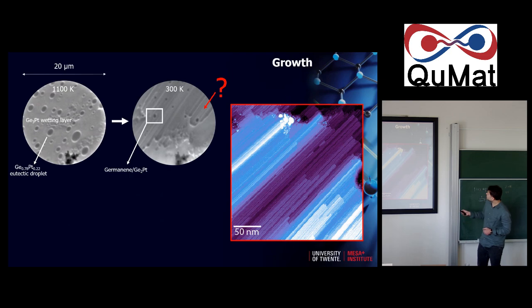If you look with STM, they look like this. They're parallel arrays of something that's very elongated, and they can even run up to a micrometer distance. So they're quite long, very narrow, and parallel next to each other, especially in these high density areas. Recently we could optimize this process, and we realized that if we don't wait long enough at this high temperature and simply flash anneal, the droplets do not have the time to accumulate a lot of platinum and to coalesce together.